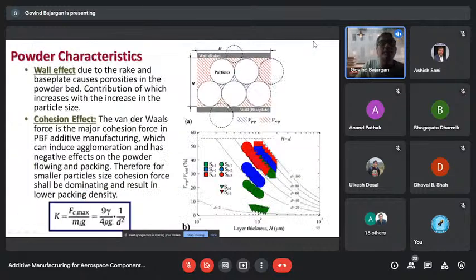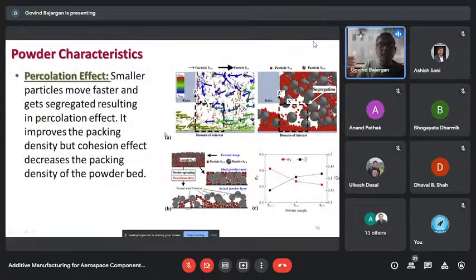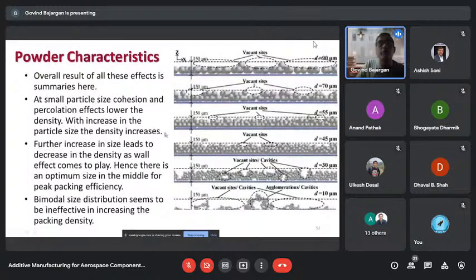Another point is the wall effect. The top rake is moving and the bottom build platform is there, so some powders which are hindered by these two walls will be pushed away. So the rake and base plate cause porosity in the bed. This contribution increases with increasing particle size. If my particle size increases, the wall effect contribution will lead to lower packing density. Then there is also a cohesion effect, when the powders agglomerate, and this tendency is more in the finer sizes. All these studies have been done by researchers, and I'll just come to the final conclusions.